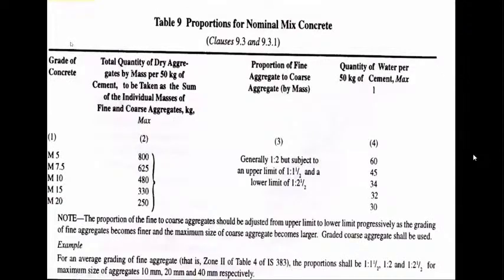the leftmost column gives you the various grades for which you can design the nominal mix. Starting from M5 up to M20, you can always very well see that M25 is not there. So you can use this table only up to these grades. The second column gives you the value of how much aggregate you should use per 50 kg of cement. The title is total quantity of dry aggregates by mass per 50 kg of cement.